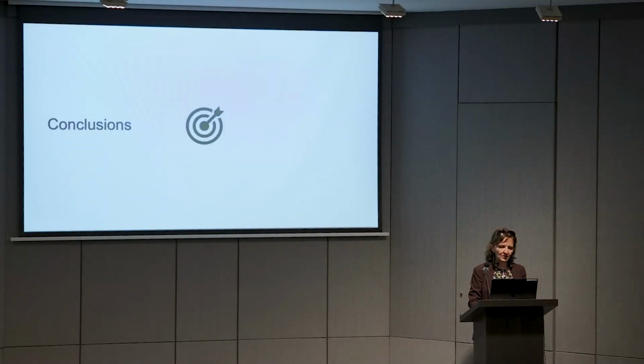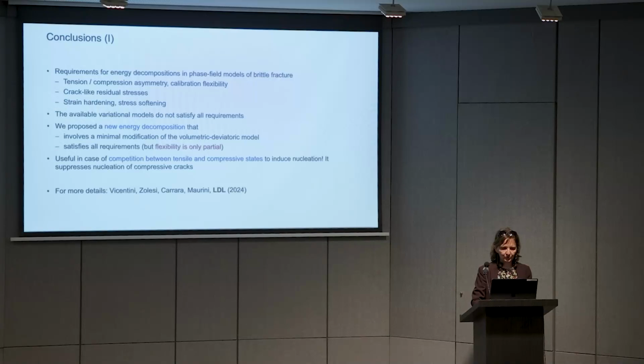Okay, then we were also doing the numerics. The numerics is pretty standard, so I'm ready to draw some conclusions. We've been talking about the requirements for energy decompositions in variational phase field models of brittle fracture. These are tension-compression asymmetry, crack-like residual stresses, strain hardening, and stress softening. We have seen that the available phase field models do not satisfy all requirements. So here we proposed a new energy decomposition where